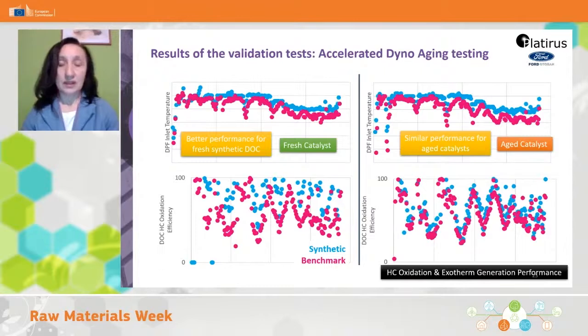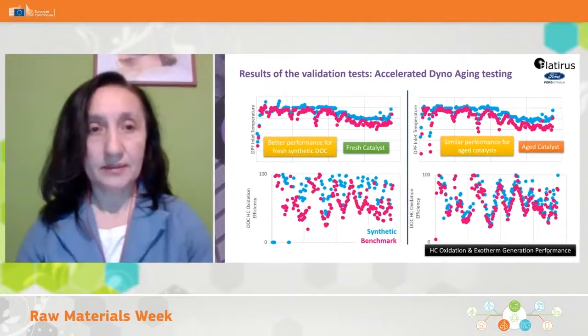So in the graph on the left side of the screen, you can see the results for the fresh state catalyst, and on the right side, the aged state catalyst. You can see that at the fresh state, the Platirus synthetic PGM yielded a very high hydrocarbon oxidation efficiency. Then it is also able to reach a very high temperature, that is 500 degrees, that is the desired temperature. At the aged state, the two catalysts show quite similar oxidation efficiency, and the temperature profiles are also very similar. Okay, this concludes the validation test. I think that Esther will be next.